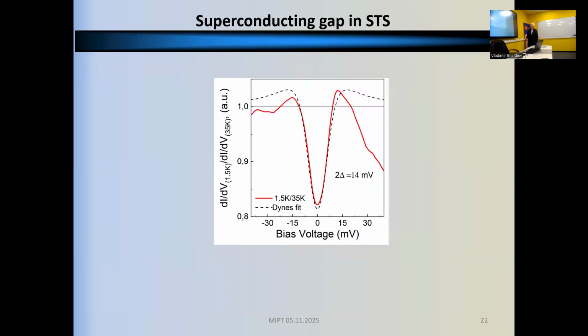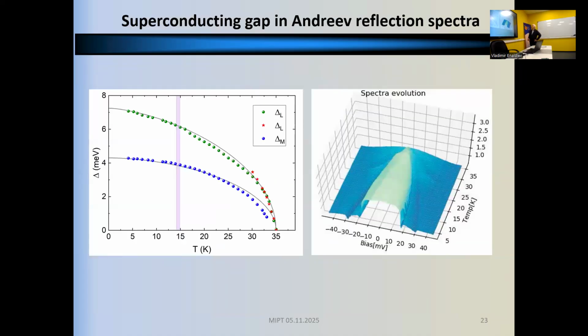By doing STS spectroscopy, we could obtain more information because, as I said, the tip doesn't come close to the superconducting layers. But another technique, Andreev reflection spectra, provides much more detailed information. Two gaps were seen here. I don't know why; sometimes one can see three gaps, sometimes two. Nevertheless, there is nothing specific at the temperature of magnetic order. So the superconductivity seems to be completely unaffected by the ferromagnetic order.